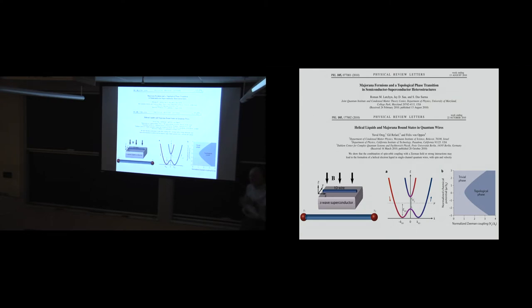Normally, if you add enough magnetic field that the Zeeman energy exceeds the pairing energy of the gap of the superconductor, you destroy superconductivity. But in the presence of strong spin-orbit coupling, that's not true. You can add enough Zeeman energy that exceeds the superconducting gap, and all that results is the topological phase. So far, so good.